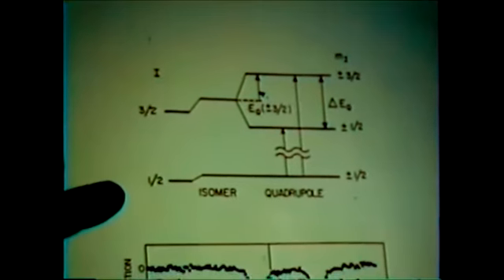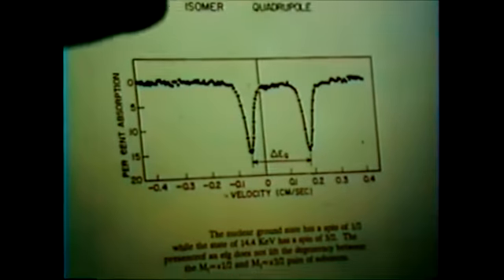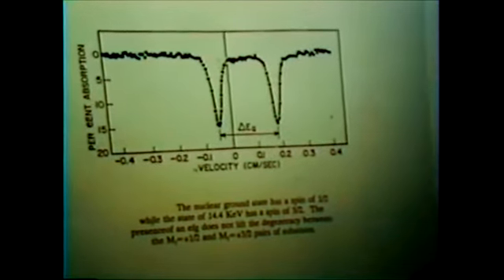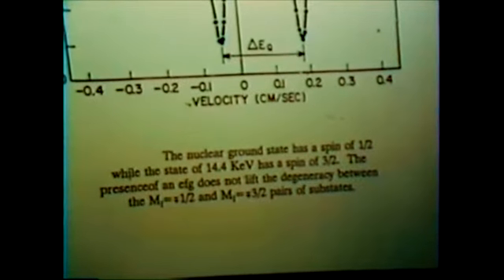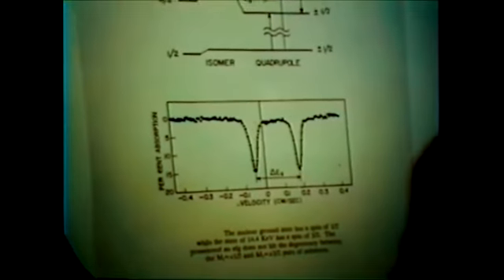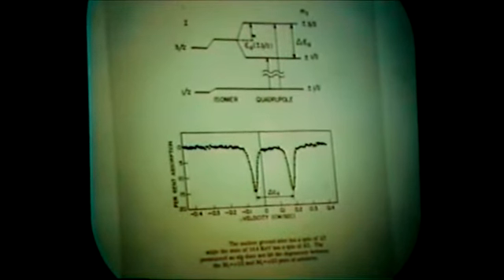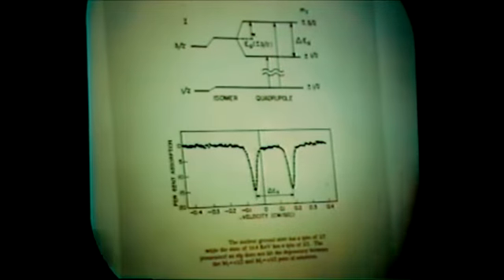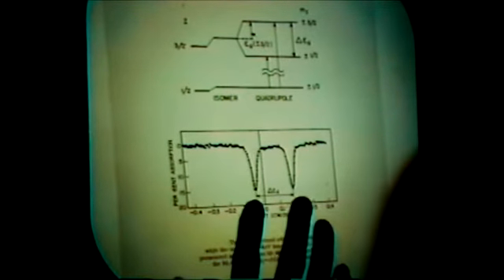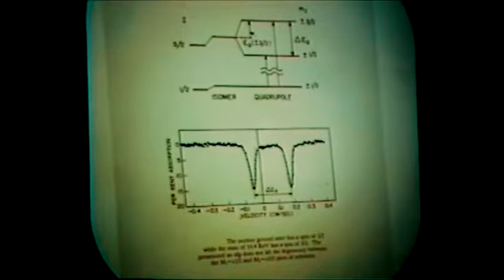Now, if you have a quadrupole interaction, this is the state of the nucleus, of course, you excite from one half to three halves. And if you have isomer shift, it's nothing but a shift. You shift the ground state and you shift the excited state and you end with a total shift. But if you have a quadrupole interaction, it doesn't lift the degeneracy of the ground state, but it partially lifts the degeneracy of the excited state. And so you have a possibility of two transitions, from the ground state to the plus or minus one half or to the plus or minus three halves. And if you have the proper energy by the Doppler shift, then you'll have two resonant absorptions. You'll have two lines. And the difference between the two lines is simply the quadrupole splitting.